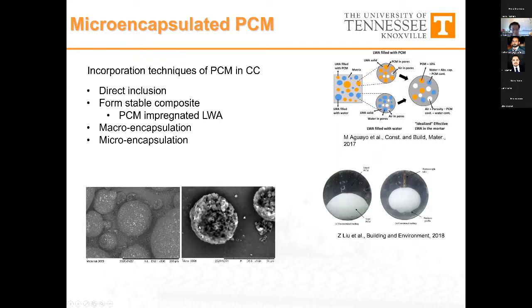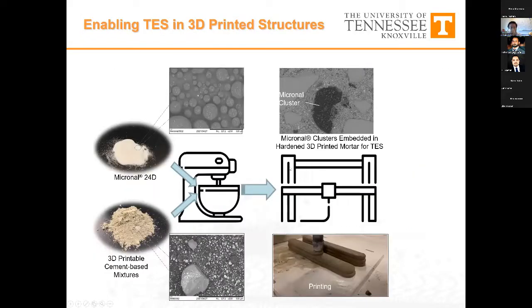So the example that we take here is polymer encapsulated PCM, which is the most well understood, well studied functional additive in the thermal space, which is basically a polymer capsule with a paraffin wax core that can go through phase change around 20 to 22 degrees Celsius in this particular case. And this particle comes in very small capsules. Roughly the diameter is about 2 to 3 micrometers, and often the material manufacturer would agglomerate them into large clusters for ease of handling.